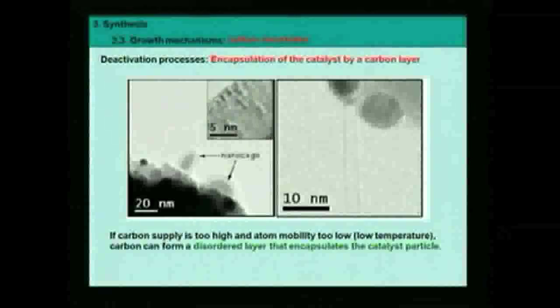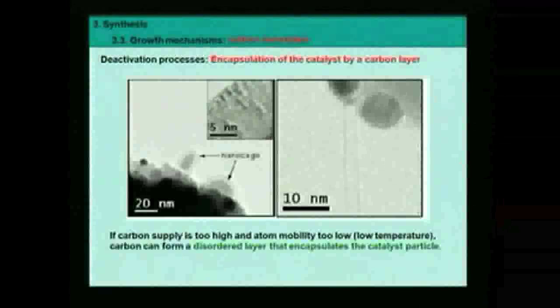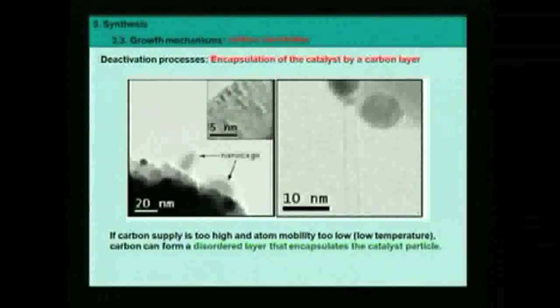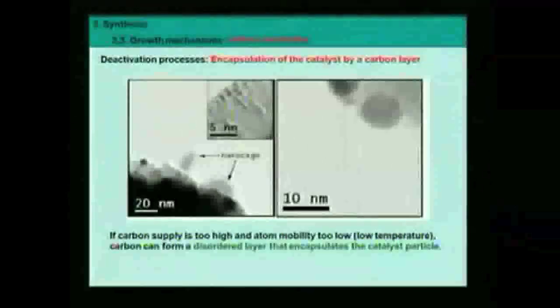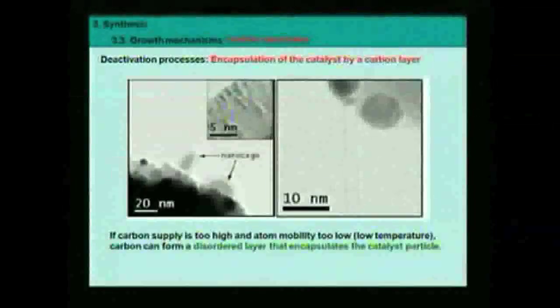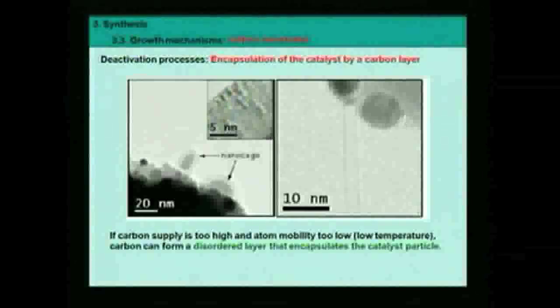Here, if the migration of carbon atoms is not fast enough, you increase the temperature. Why? Because diffusion, surface diffusion, bulk diffusion is thermally activated. Not all processes are thermally activated, but most processes involving breaking chemical bonds are thermally activated. And as I said, migration of atoms on the surface means breaking bonds to move. So we can increase the temperature. So here, to prevent that, it's better to have high temperatures, to have fast migration of carbon atoms at the surface, and not provide carbon atoms too fast.